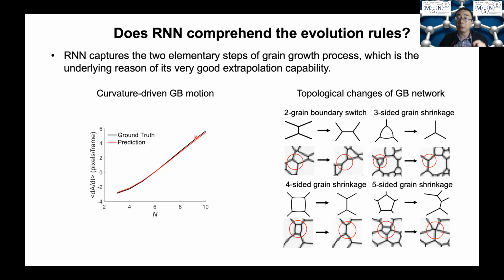So here, the rate of area change of a grain is controlled by the curvature of the grain boundaries. And the grain boundary curvature is further controlled by the number of sides the grain has. And what we found is the RNN model, after training, can accurately predict this dependence of the grain boundary movement velocity as a function of the number of sides. Right? So that captures this elementary step.